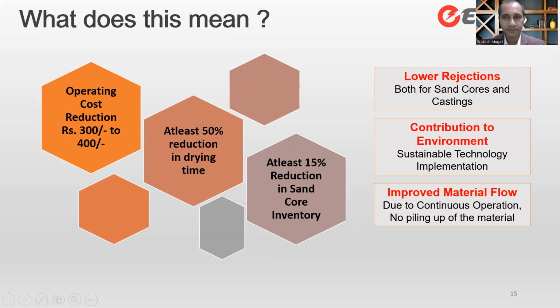So what do all these benefits mean? What do the advantages translate to in terms of the end economics for the foundries? Number one, the operating cost is very low compared to what we have seen in the benchmarking oven that we built. There is a cost reduction of 300 to 400 rupees per ton of drying compared to conventional drying methods. There is at least a 50% reduction in the drying time compared to any other method. And then there is at least a 15% reduction in sand core inventory. This is based on how you can implement just-in-time and how you can use these core inventory limitations.